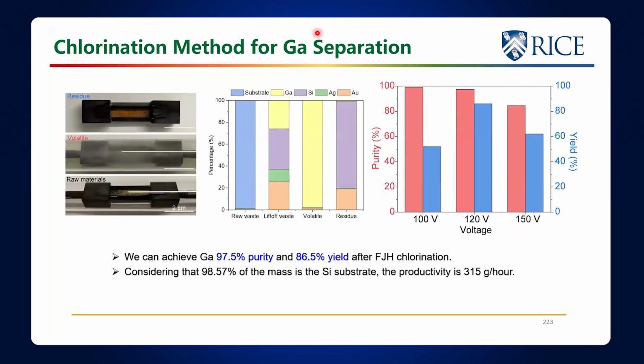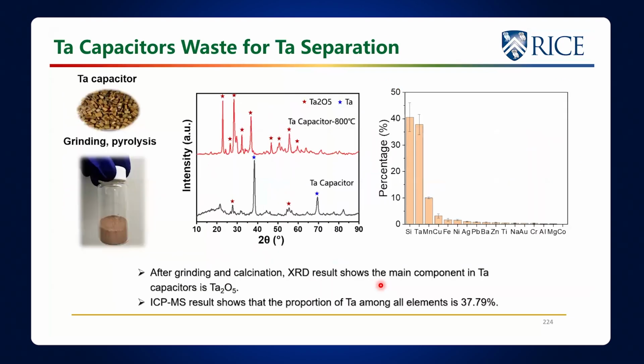So this is what it looks like. Here are the raw materials, and then here's the evaporated phase over the top, and here's the residue. So here's the raw waste, the substrate you get rid of, and here it is with gallium, which is what we want to go after. When we brought it up to that flash temperature, we get mostly gallium with a little bit of other impurities. So we could get gallium at 97.5% purity and 86.5% yield, again meeting the DARPA milestones. DARPA puts upon you these different milestones.